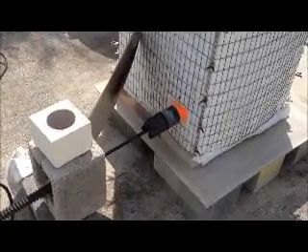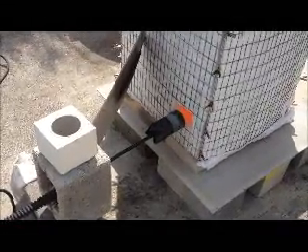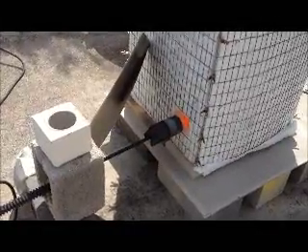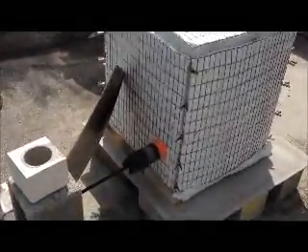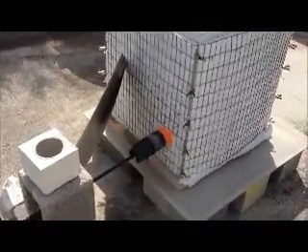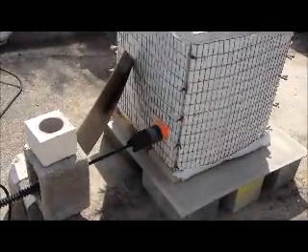I've got some pieces that, because of time constraints, I need to do a raku firing on tomorrow. I built these pieces the day before yesterday, and I was worried about getting them dried out enough, so I put them in the kitchen oven at 170 degrees and left them there for about six hours. I had no cracking. It's raku clay and white stoneware clay on the various pieces.